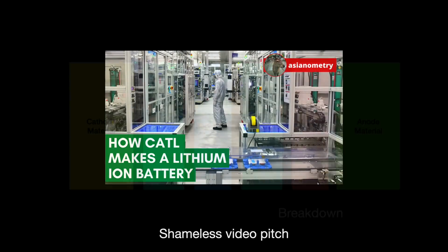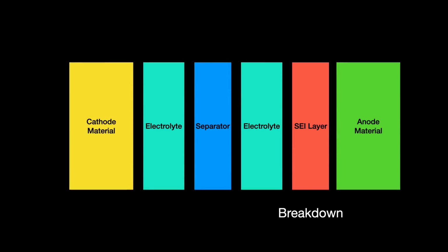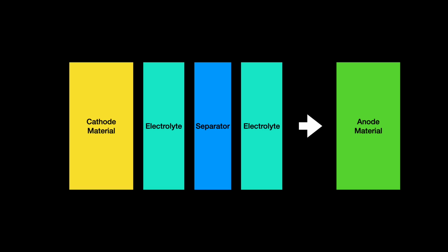Anyway, when the temperature gets too high, usually at around the 90 to 120 degrees Celsius level, the SEI breaks down. This generates additional heat and creates carbon dioxide in the process. The chain reaction can now continue. With the SEI layer gone, the barbarians of the electrolyte can breach the gates and react with the anode. This generates yet more heat, as electrolyte reactions tend to be especially hot.